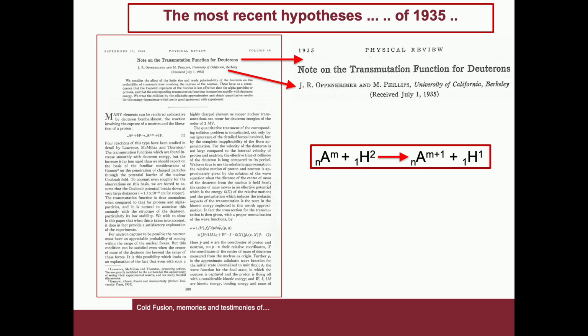The scheme experimentally demonstrated by the two authors is that in which an atom with a given atomic number colliding with a deuterium nucleus produces an atom with the same atomic number but with an increase in mass of 1 unit, releasing a proton. That is why they are called proton-deuteron stripping reactions. It's an example of the possibility of transmuting one atom into another while maintaining the same atomic number, thus forming an isotope of that atom. This was Phillips' proposed mechanism for our reaction, and with that scheme, the energy value we found is justified.